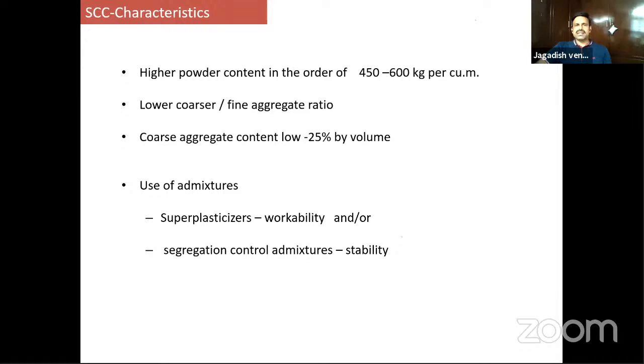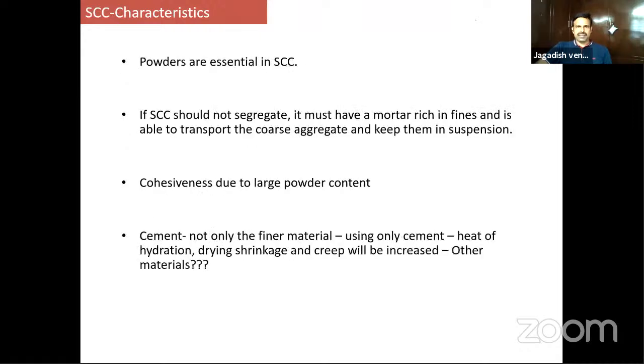And superplasticizers and segregation control admixtures are used in making SCC. As I mentioned, it requires 450 to 600 kg per cubic meter. You cannot use cement alone because IS allows no more than 450 kg per cubic meter. There are problems like heat of hydration, drying shrinkage, and creep will increase. So you have to look for other materials.